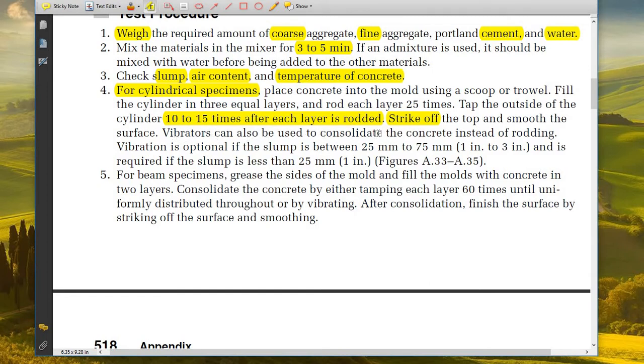Vibrators can also be used to consolidate the concrete instead of rodding. Vibration is optional if the slump is between 25 millimeters to 75 millimeters and is required if the slump is less than 25 millimeters.